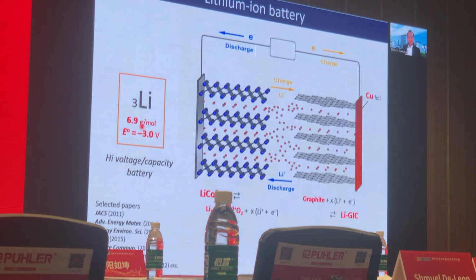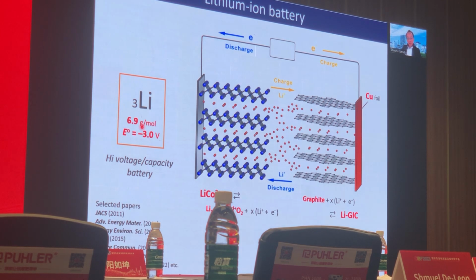When I was a student, we learned that lithium is the theoretically best choice for lightweight, high power, high energy density batteries because of the lowest E0 and also the lowest atomic weight among any metal elements. Based on this feature of lithium, the combination of lithium cobalt oxide and graphite has worked well as a lithium-ion battery over the world and over 30 years. By charging this battery, lithium moves from the positive to the negative electrode. Then a lithium intercalation compound, lithium GIC, is formed on the negative side on the copper current collector.